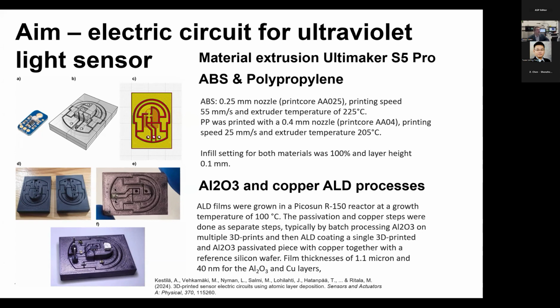The first thing here was to find suitable materials that we can join together, not with huge mechanical properties, but so that we can print them together. One should be where this ALD process sticks very well, and the other where the ALD process doesn't stick at all. We tested plenty of different materials in this ALD process, and then we figured out that ABS works very well, and on the other material the coatings don't attach. So it is a very good material pair for this kind of selective coating.